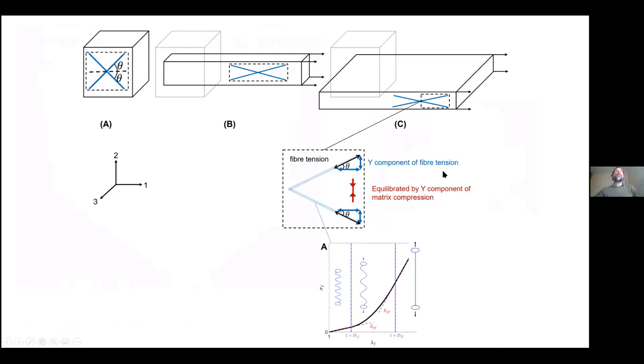So this is work that Beruze has done as part of ASSIST. If we take this block of material and we say we have two fibers connected to this matrix, and the fibers are at an angle theta, when we stretch this block of material in the horizontal direction here, you can see these fibers are starting to become more aligned. But when we stretch the material, we're stretching the fibers. And this puts tension into the fibers.